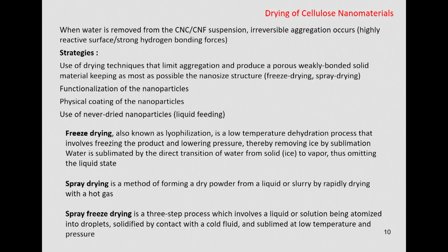Drying of cellulose nanomaterials. So when water is removed from the suspension, we have an irreversible aggregation, of course, because of the OH group from the surface. Some strategies have been proposed, like, for example, the use of drying techniques that limit aggregation and produce a weakly bond solid material, keeping as much as possible the nano size. Can be freeze drying.